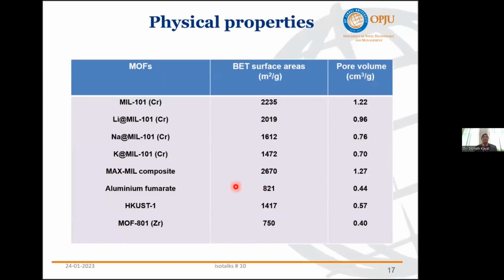Okay, so basically the BET surface area of the synthesized porous materials: we found that for MIL-101 chromium, we got a surface area of 2235 square meters per gram, and whenever it is doped with some alkali metals, there is some decrease in the surface area. And for the composite material, we got some increase in the surface area to 2670